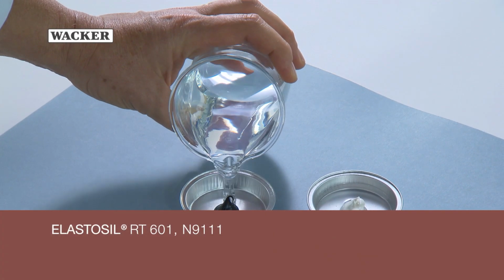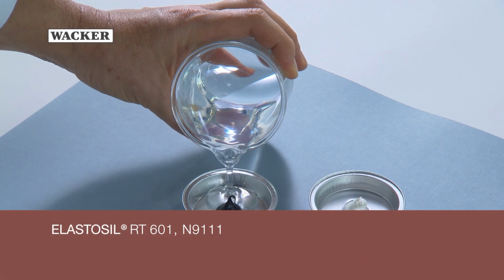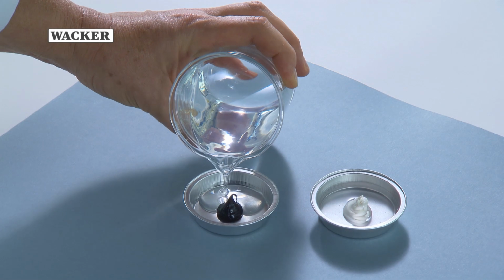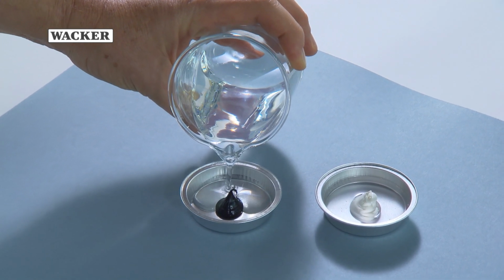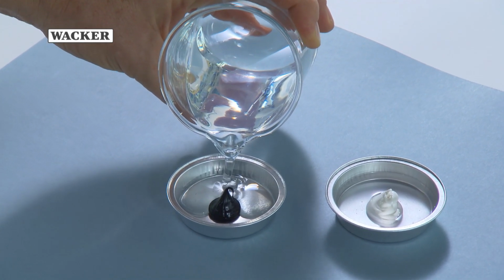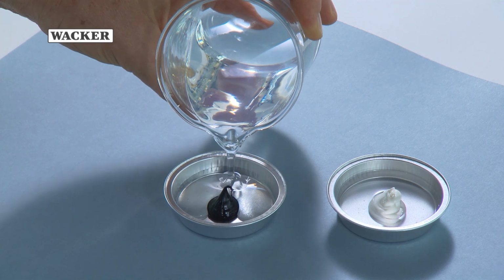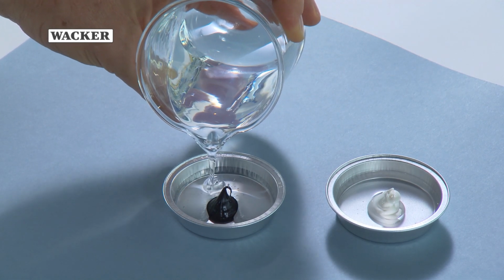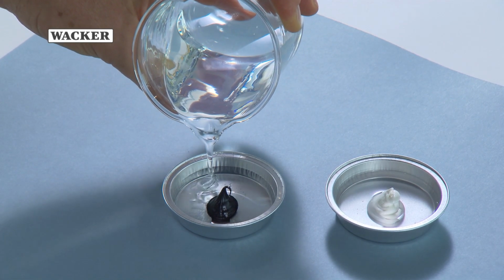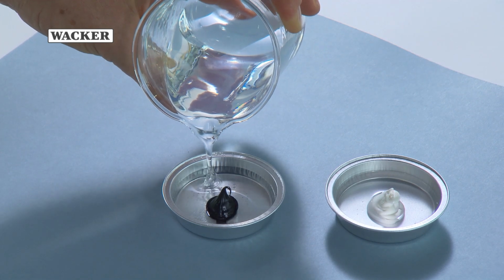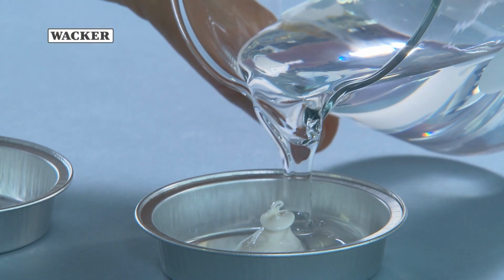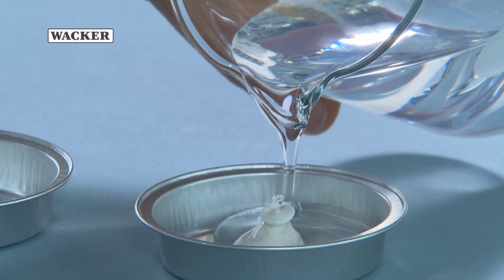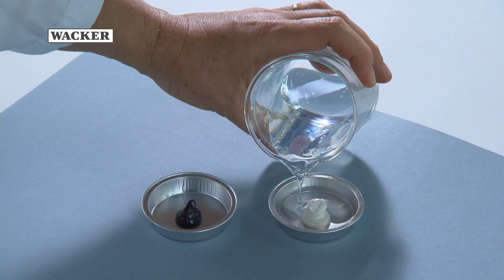Even processing addition curing silicones together with condensation curing silicones generally produces contact inhibition. In this case, it is the tin compounds in the condensation curing silicones that poison the platinum catalyst. Silicones that contain titanium catalysts instead of these tin compounds do not exhibit this behavior, however.